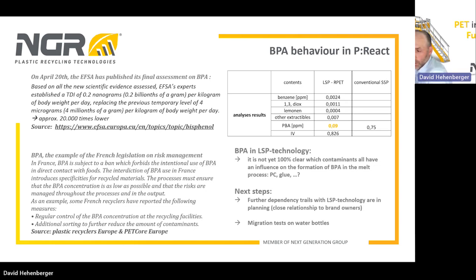But also here it is good when you have a good cleaning efficiency in the recycling process in order to minimize BPA in the pellets. And we found here some numbers, one number was 0.09 ppm, which means 90 parts per billion. We definitely would like to analyze and research further in this matter. Our next steps are further dependency trials, where we also would like to purposely add contaminations like polycarbonate and glue in order to find out what the cleaning performance of the LSP is. And finally, we also would like to do a migration test of these bottles.